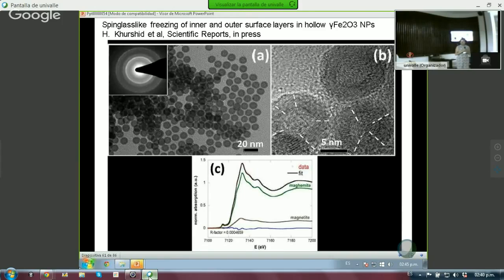At the synchrotron source, we did what's called XANES. There you just look at the K edge of iron and you get the spectrum. And what you can see is the data and the fit. What we have up is the maghemite and down the magnetite. And when we combine them and fit them, we have a very nice fit, which is represented on top. And this contains about 75 or 80% of maghemite and 20% of magnetite. And then you have the bottom one, the R factor, which is, of course, the statistics of the fit. And as you can see, we can determine the amount of each valence of the iron.